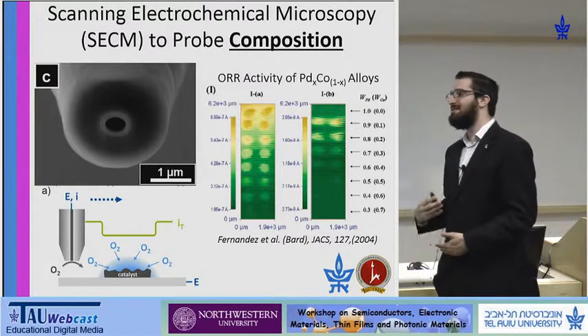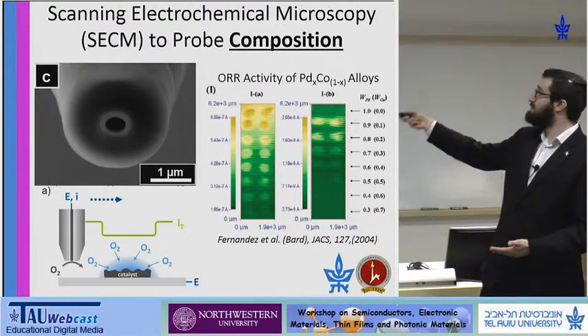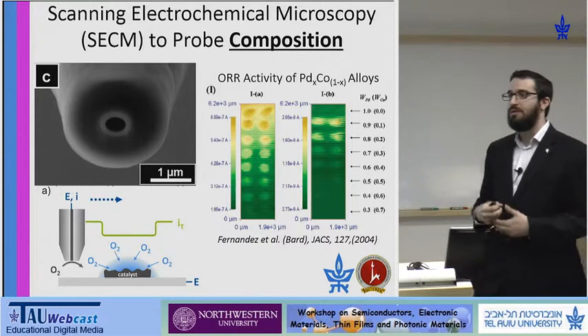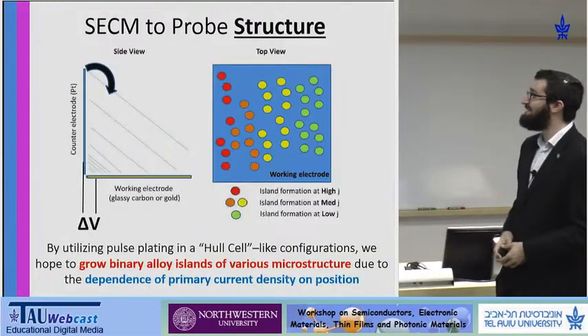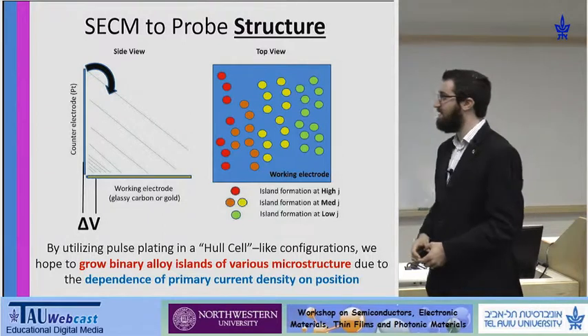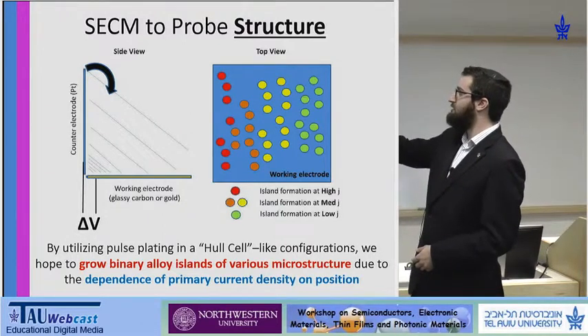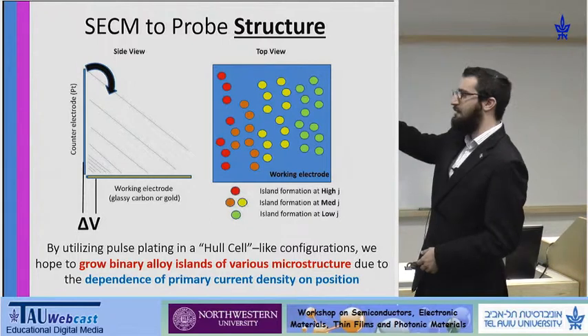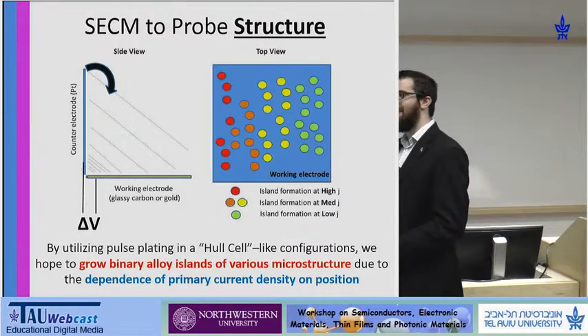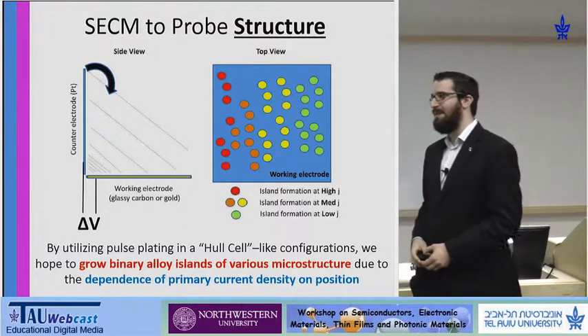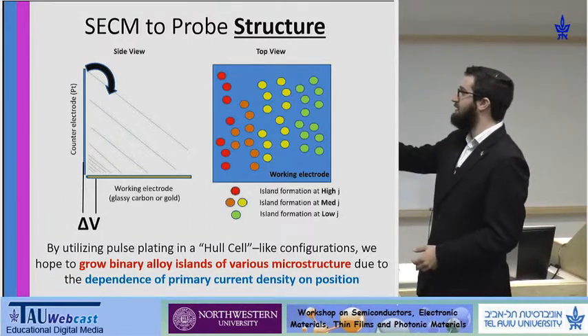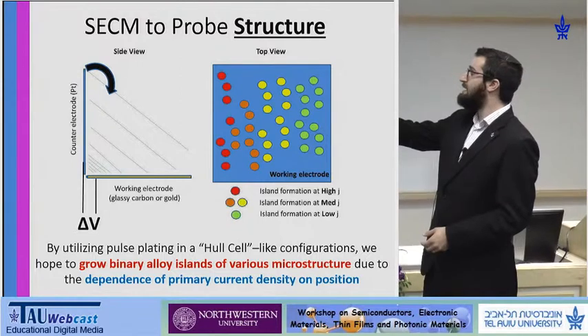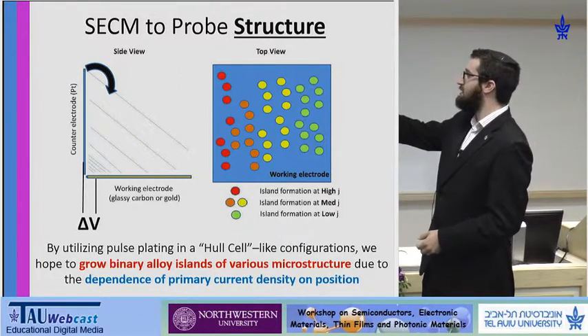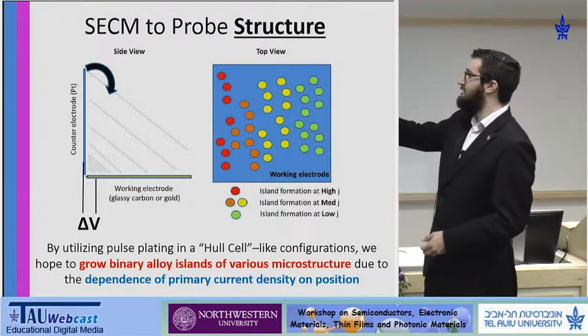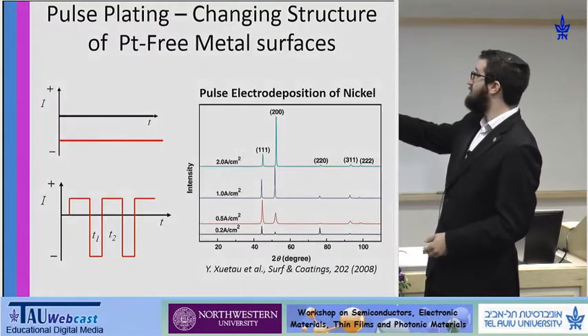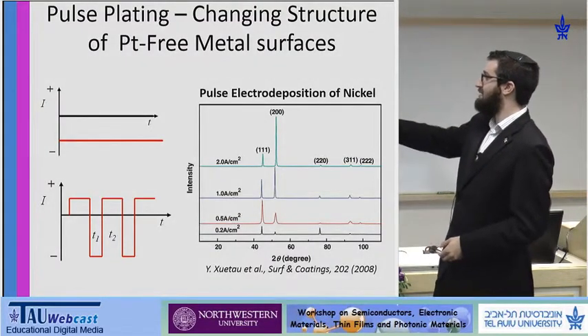We want to do this technique, but instead of changing composition with respect to position on the electrode, we want to change the microstructure. And what we find is this could be possible with a Hull Cell-type device where the working electrode and the counter electrode are held at some angle with respect to one another, which is to say they're not parallel. This means the primary current distribution will be dependent on distance between the counter electrode and the working electrode, which means we can apply effectively a different current distribution that's dependent on the position. And as I showed a few slides ago, the structure is dependent on the current density.